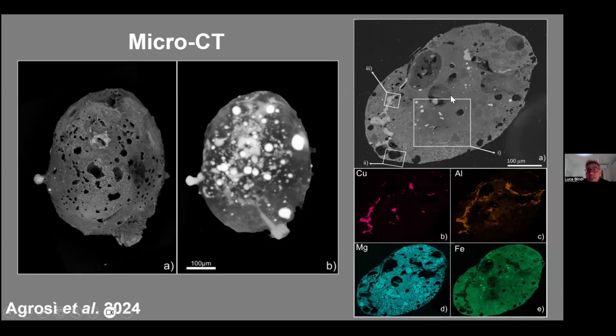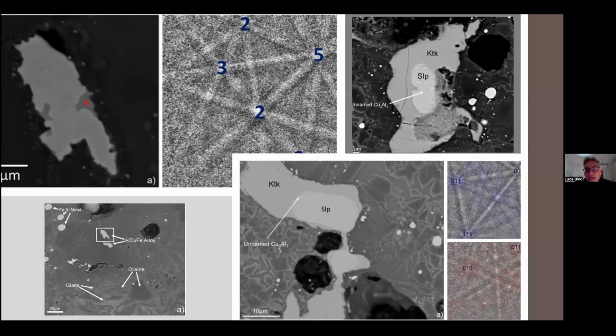And look at the inside, look at the polished regions, the inside of this spherule, and look at the chemical maps. Several regions are copper and aluminum rich. And these are the compilations of scanning electron microscope images where you can see the sharp contacts between the copper aluminum and the silicates. Look at the image in the middle, look at these relict olivines. And again, I would like to show you in advance the oxygen isotopes we got recently on this sample. I would like to show you all the oxygen isotopes of all the known copper aluminum bearing extraterrestrial objects plotted together in the end.